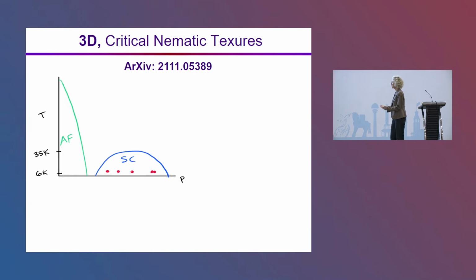Now, another curious thing that came up here. We can say that there are 3D critical nematic textures happening in BSCCO. I call them nematic because of the broken rotational symmetry. A liquid that breaks rotational symmetry is a nematic. Since we're tracking the stripe orientations, we're tracking just the nematic order parameter. So this is a generic phase diagram of cuprate superconductors, temperature as a function of doping.